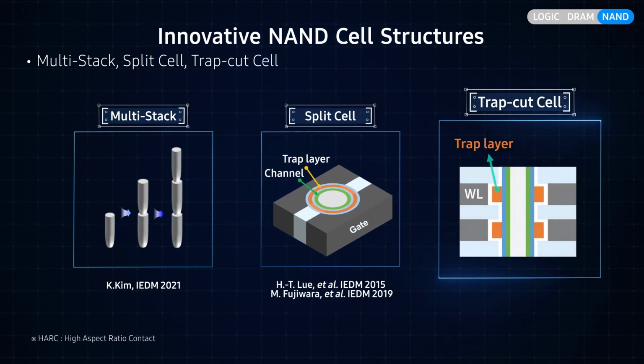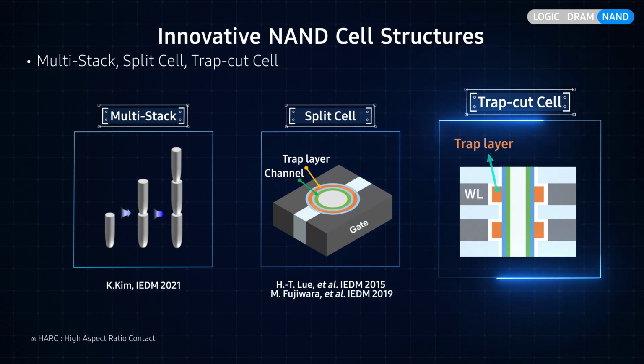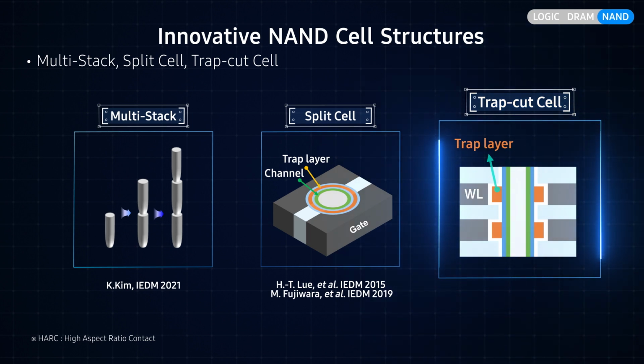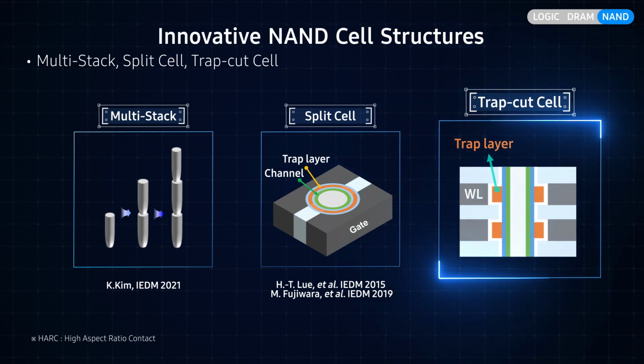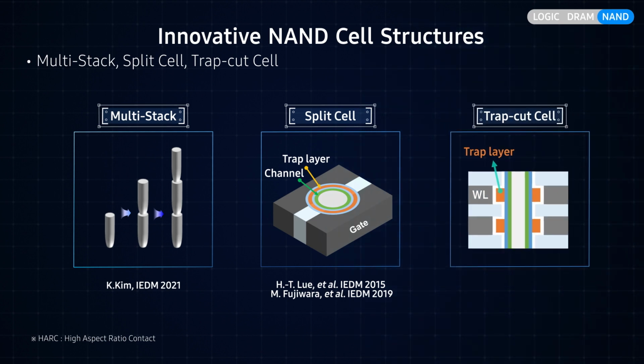On the other hand, in trap-cut structure, vertical pitch of the single layer can be scalable because by cutting a charge trap layer, we can greatly suppress the interference between neighboring cells. However, these structural innovations can mitigate the challenges of stack height increase, but they cannot stop total stack height increase because more layers must be stacked with ongoing evolution of generations, thus aggravating cell current and mechanical stability.